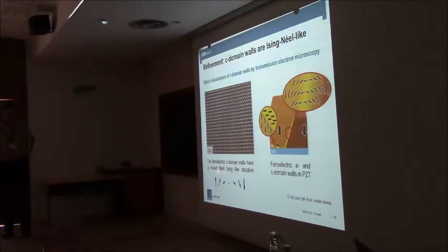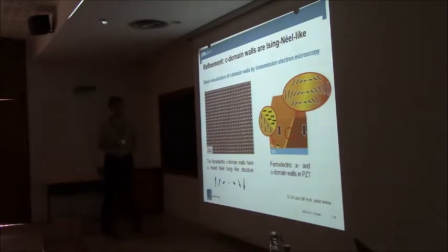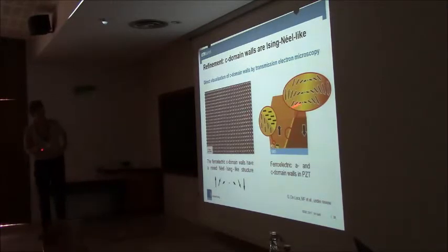So it's a mixed Néel Ising-like domain wall. At the same time, polarization rotates and it becomes smaller. That's something that you can really otherwise not see easily, unless you then do your transmission electron microscopy. And it's only there for these C domain walls up to down. It's not there for these 90-degree domain walls A to C.